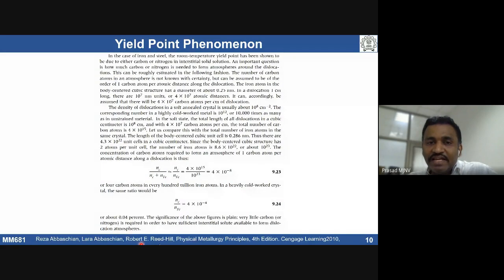This information is taken from a textbook, a very good textbook with a lot of information about the yield point phenomenon. If you see the number of carbon atoms required to pin the dislocations present in an annealed material, it's about 10^8 per centimeter square. Again, in terms of units. If you convert into meter square you get the corresponding number. But for this particular density of dislocations, we need just 4 into 10^-4 as the atomic fraction of carbon with respect to iron.